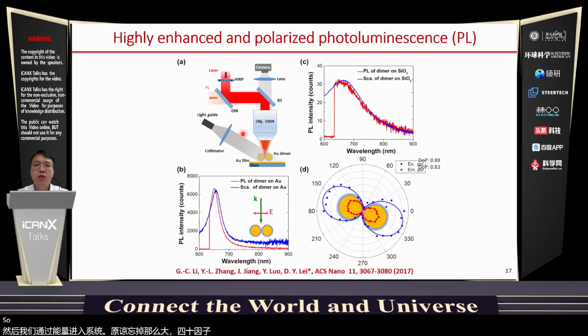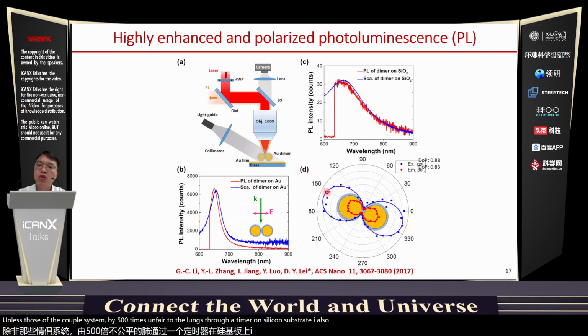The good thing with this enhanced quality factor is that we can enhance the photoluminescence of the coupled system by 500 times compared to the nanosphere dimer on a silicon substrate. And we also get a highly polarized photoluminescence response from the structure.